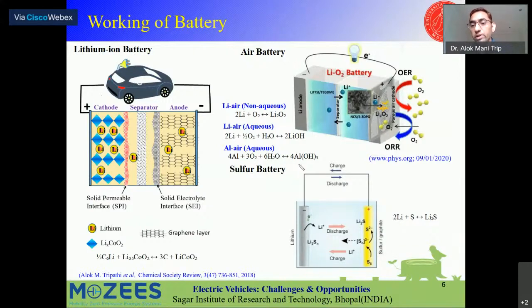So you see what benefit you are getting. Like in the lithium ion battery, you have a physical electrode. Here you have a gaseous electrode. So because of the gaseous electrode, you are able to save the weight of the battery. Because if weight increases, definitely your energy density will go down, because it's watt-hour per kg. And the chemistry is also giving some enhancement in the capacity. That's why the overall energy density of the air battery is going up.